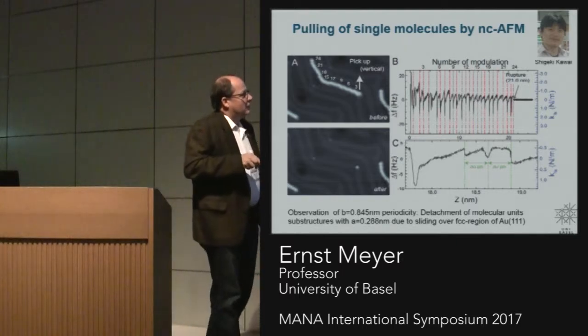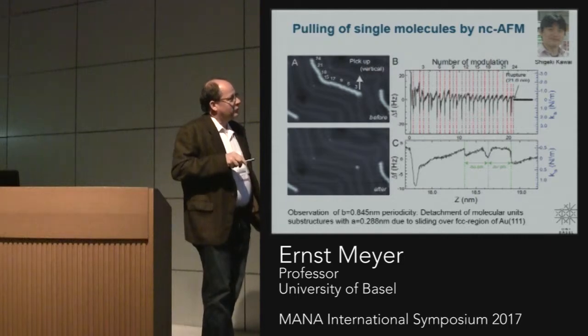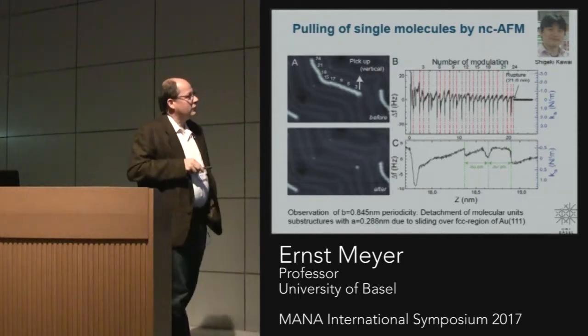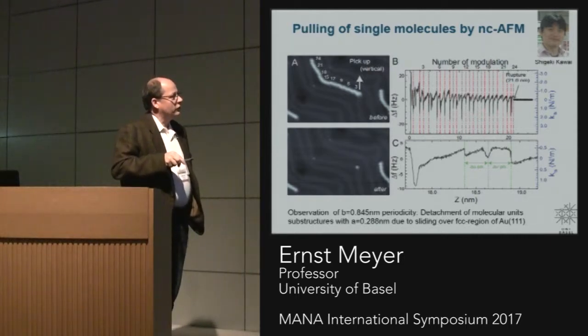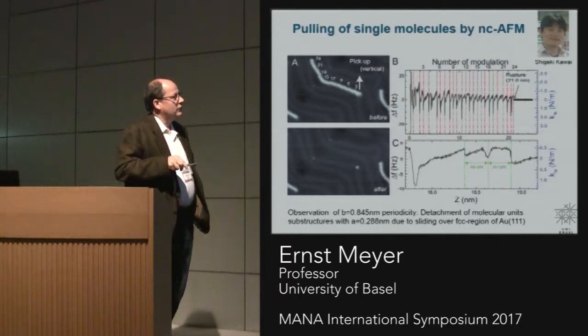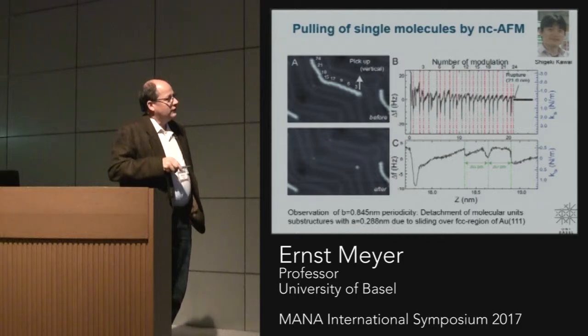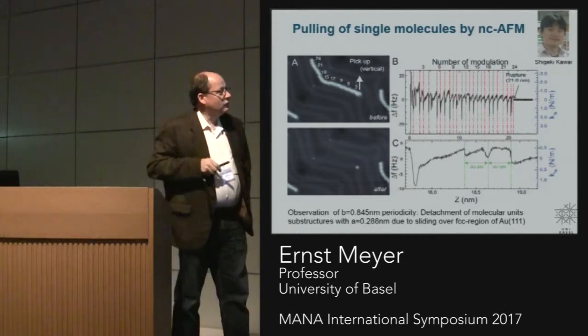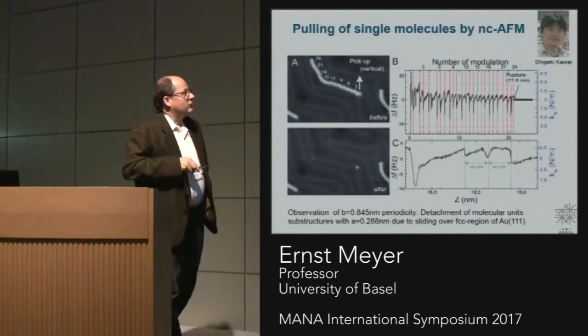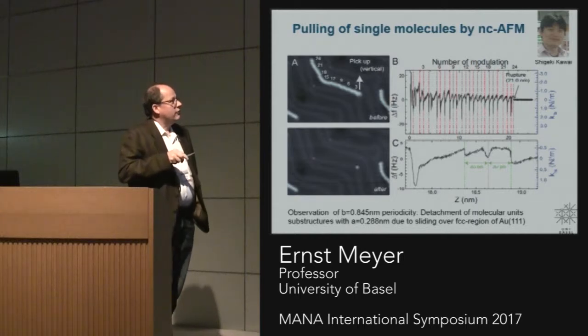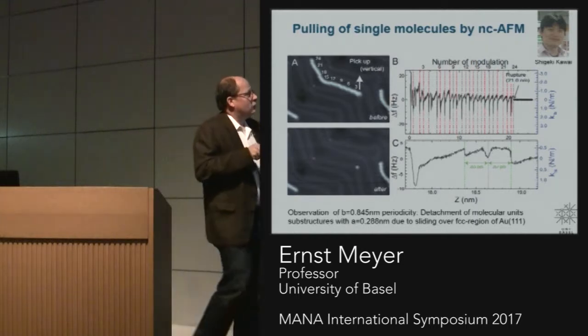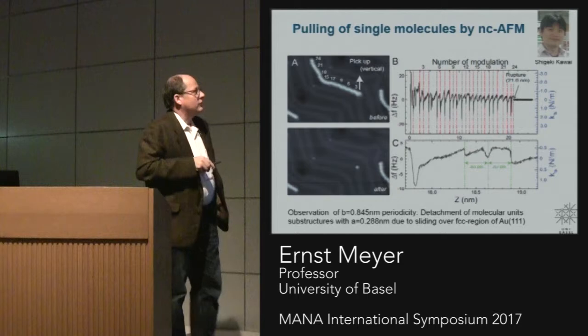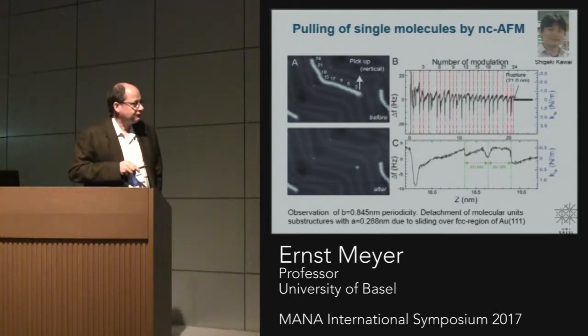There is also some substructure which is not noise here, but so if you zoom into one of those peaks here, you can see there are little fine features here, and if you measure the distances here, you see that it's related to the substrate. So the substrate here is gold. You also see this herringbone reconstruction. So the wire actually moves in the valley of the herringbone reconstruction.